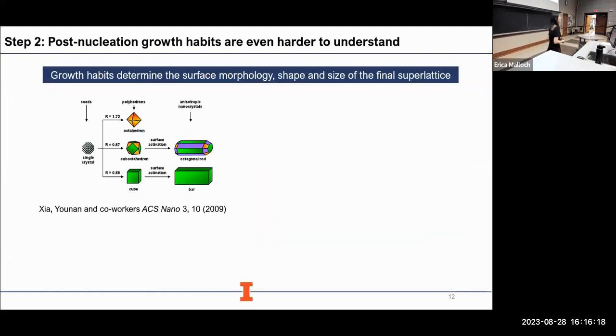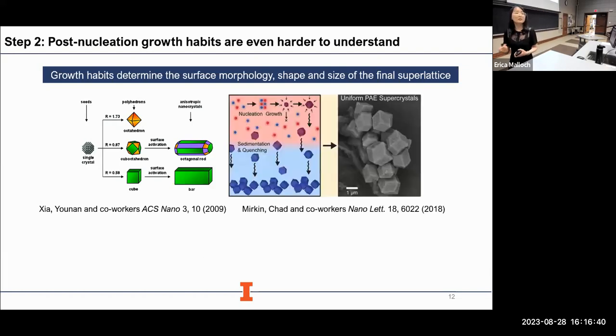The second step of crystallization is the so-called post-nucleation growth habits, which is also a concept we learned from atomic crystallization. As shown here in this example, even if you start from the same nucleus, given different growth environments, you can have crystals of very different size, shape, and surface morphology. This concept has also been demonstrated in superlattices self-assembled from nanoparticles. So we wondered what the fundamentals behind it are.